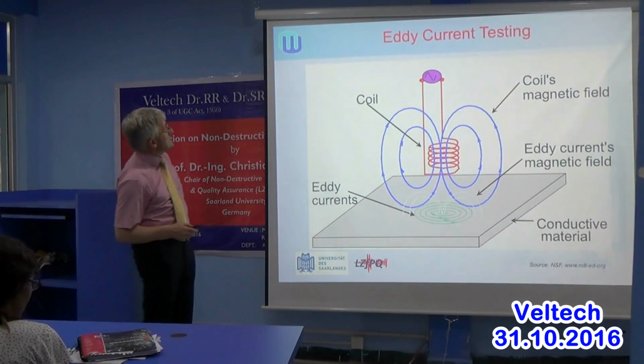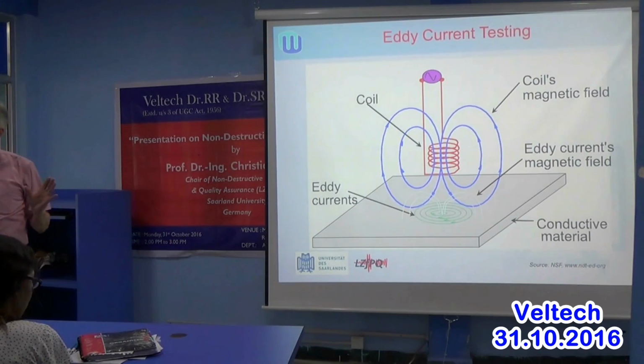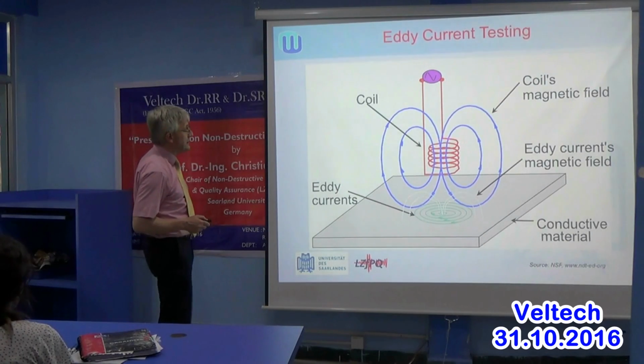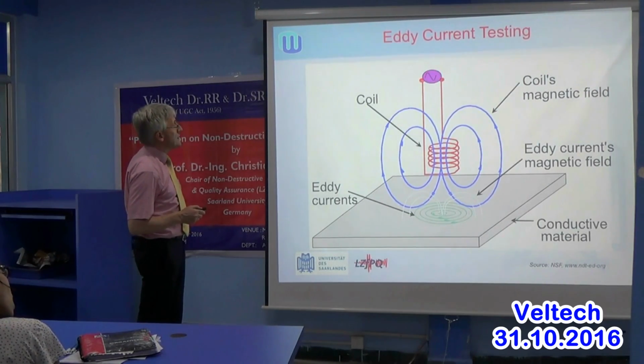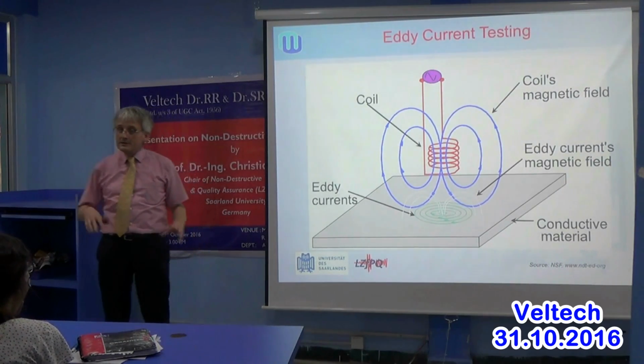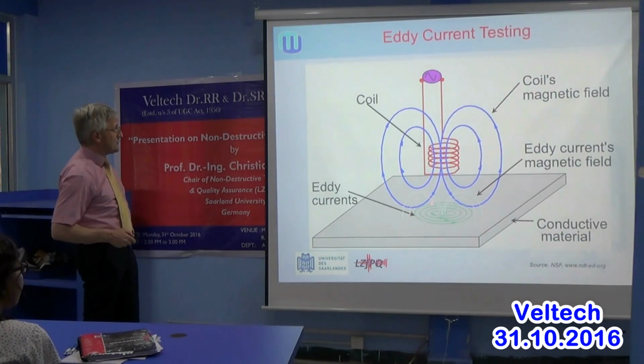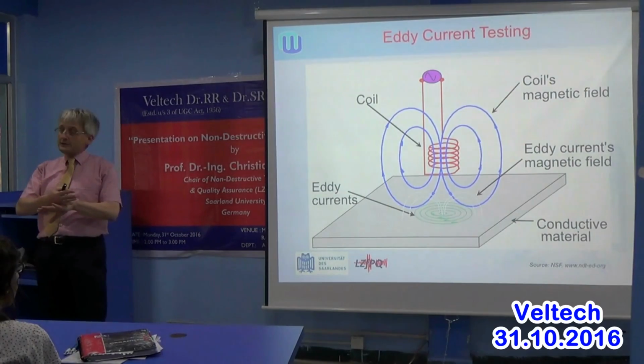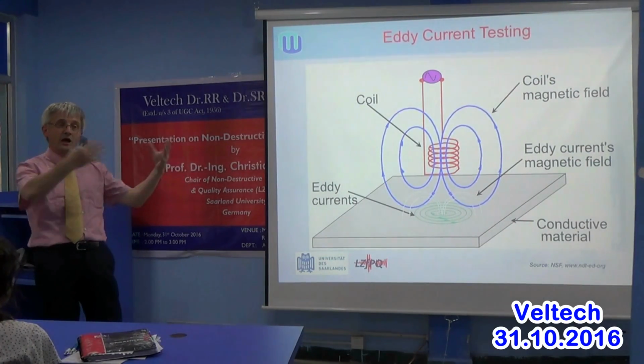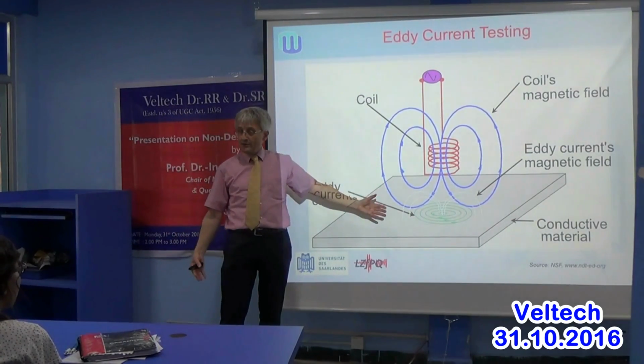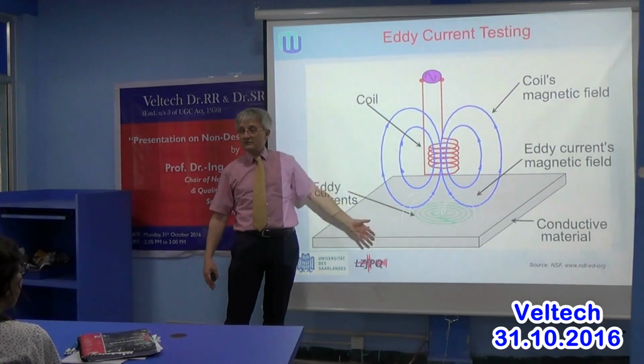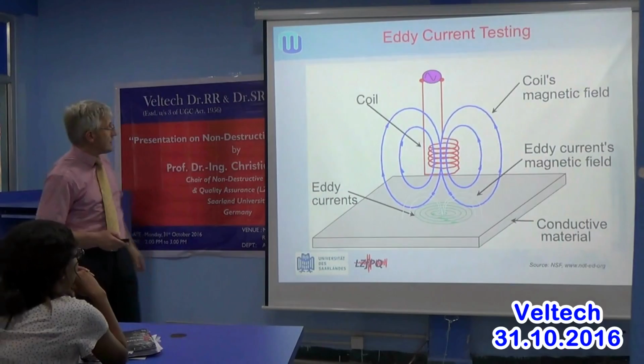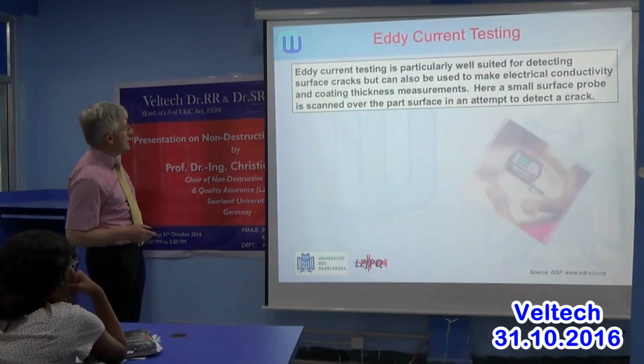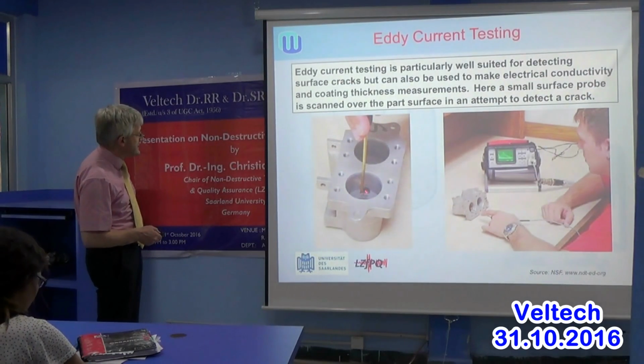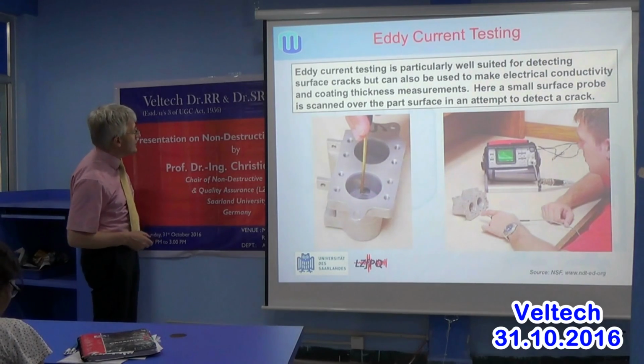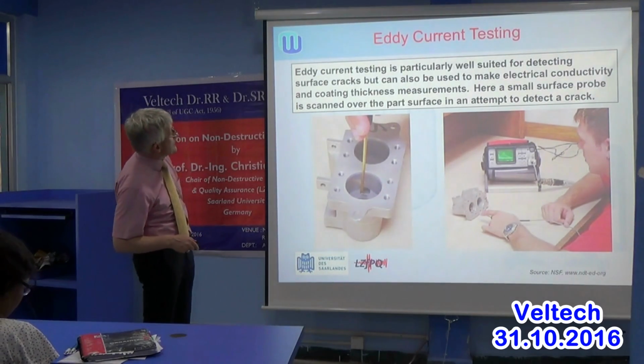Then there's a technique which is very widely used, which is eddy current testing. What we have here is a coil, and we apply an alternating current to that coil, and the alternating current generates a magnetic field. If this magnetic field interacts with something which is conductive, then we get an induction, and the change of the induction is a sign of the condition. It either tells us what material this is, or what the condition of that material is. We're not going into the details of that one, but there's a variety of applications. It's specifically popular for tiny components, for whatever we find in the holes. You see, he has a little coil here, and he inspects the surface condition, here on that cylinder or whatever automotive supply component that is.